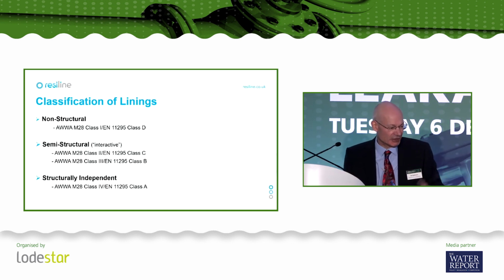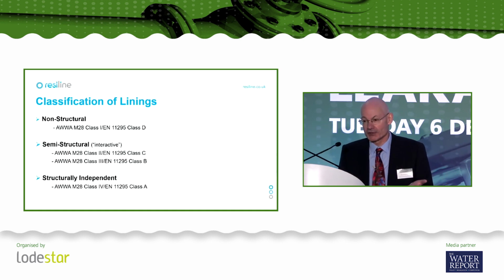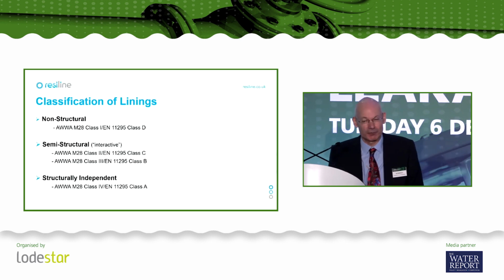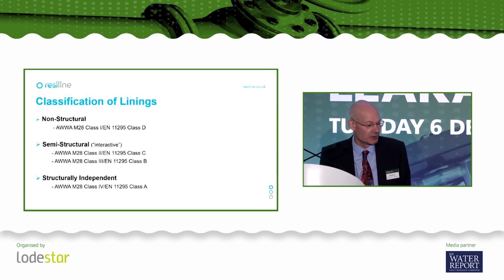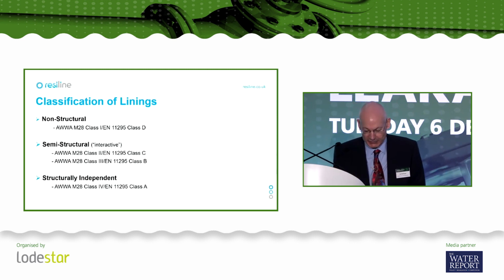Now, there are two classes of semi-structural liners, Class 2 and Class 3. The simple difference between the two is that a Class 2 liner relies on adhesion to the host pipe, whereas a Class 3 liner doesn't require adhesion. It's got sufficient hoop stiffness to be self-supporting in the absence of adhesion. And then finally, we have structurally independent liners, which some people refer to as fully structural, which are Class 4 per AWWA M28, or Class A if you prefer the BS EN ISO classification.